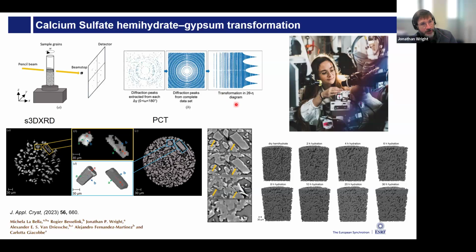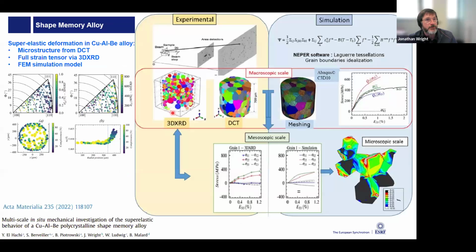So this is bassanite hydrating to gypsum. You could watch the shapes of the crystals changing, and you could watch that in 3D and in detail. And the questions they had was, how did this reaction go? And were there orientation relationships and structural relationships between these two chemical compounds? So they could watch in tomography how the crystals transform. And then this scanning 3D XRD method was then to understand which crystal had which crystal structure and how they were transforming, and to look for the different phases inside and so on.